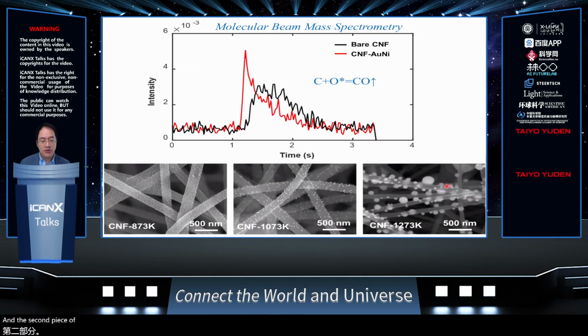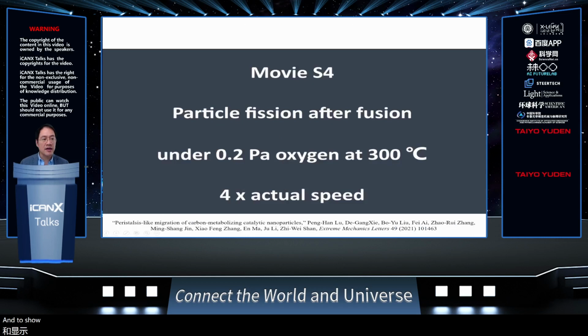And the second piece of evidence is that we actually have different kinds of carbon nanofibers. In fact, this temperature is not the temperature of heating. This is the temperature at which we pyrolyze the carbon. So this actually is a high quality carbon nanofiber with a higher degree of graphitization, so less dirt on the surface, less oxygen, sulfur, nitrogen, and so forth. But in this case, we do not get good dispersion of the nanoparticles. It is actually the not so high quality, not so well graphitized carbon fiber which has a very fine dispersion of nanoparticles.